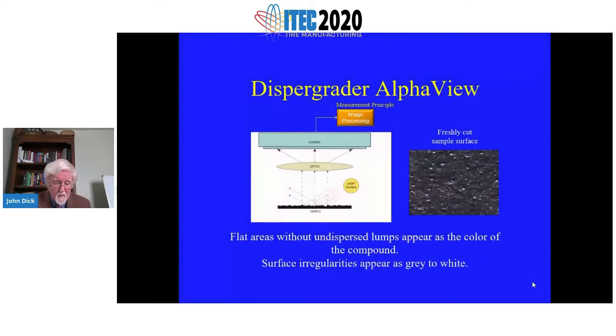The Dispergrader works on the principle of having light coming in on the rubber sample at a 30-degree angle, and that light, which reflects into the lens of the microscope, is recorded as white area, as opposed to black. And by using special equations, we can calculate the percent dispersion with various algorithms that we've worked out. Next slide.